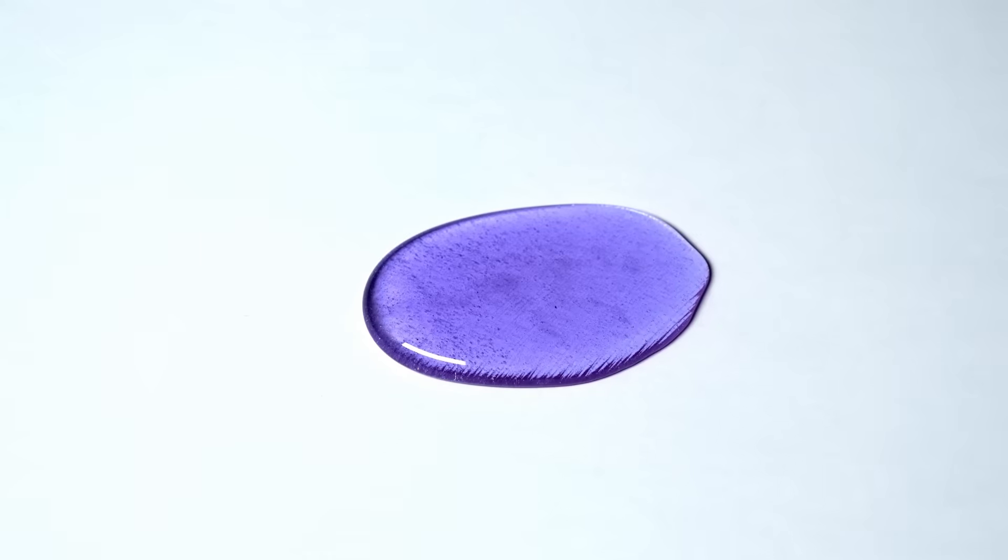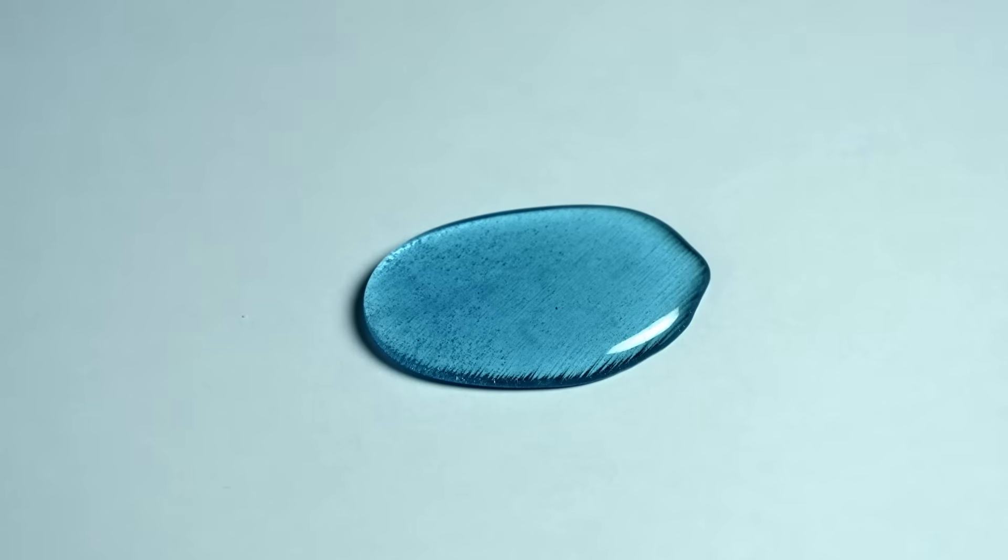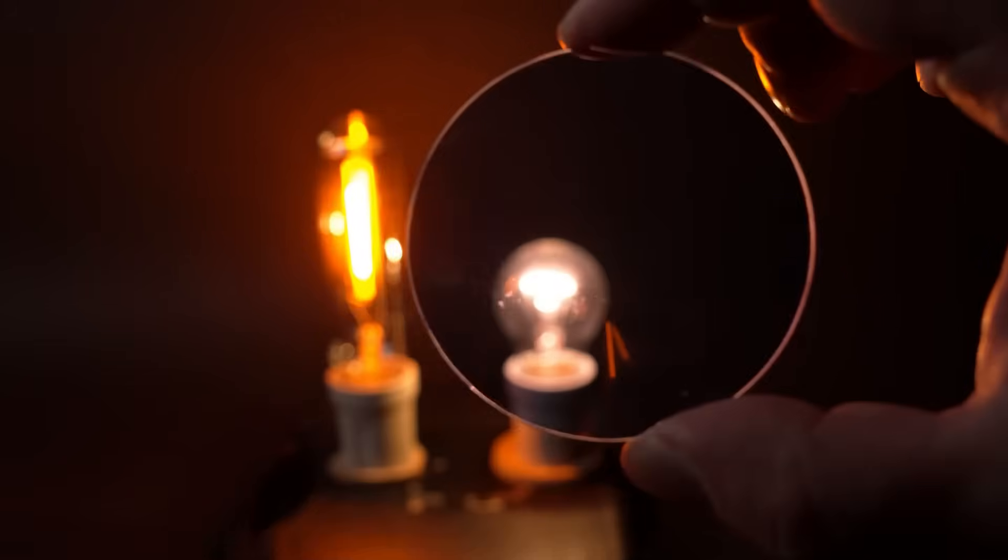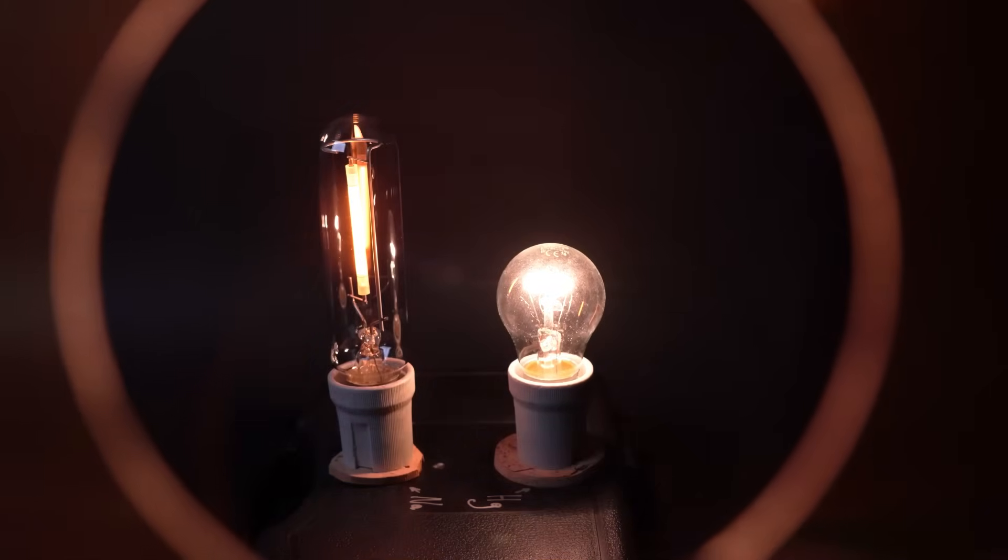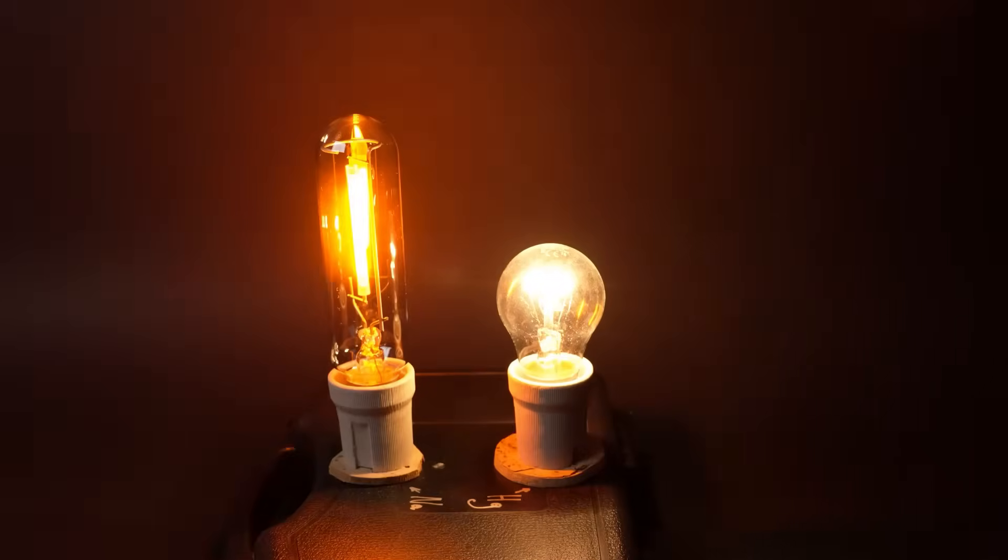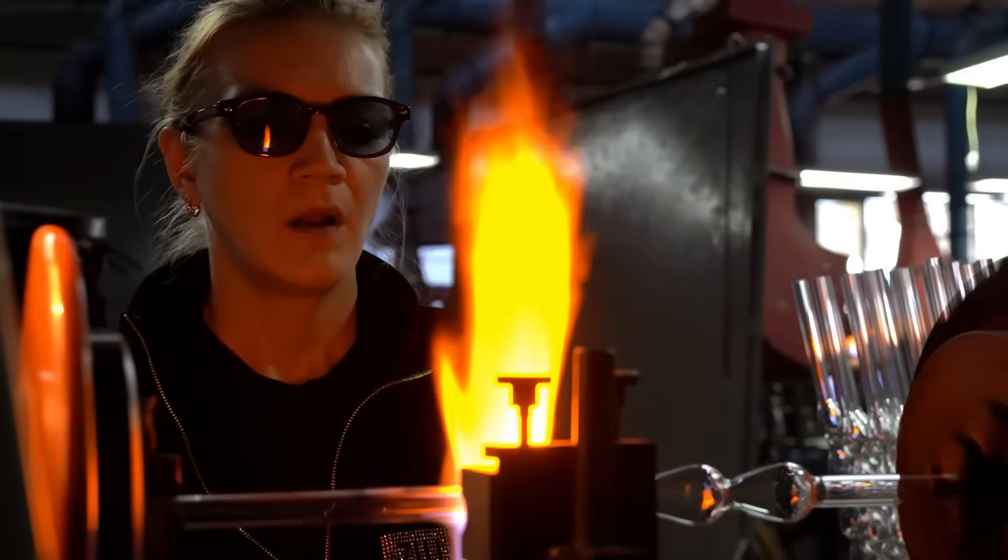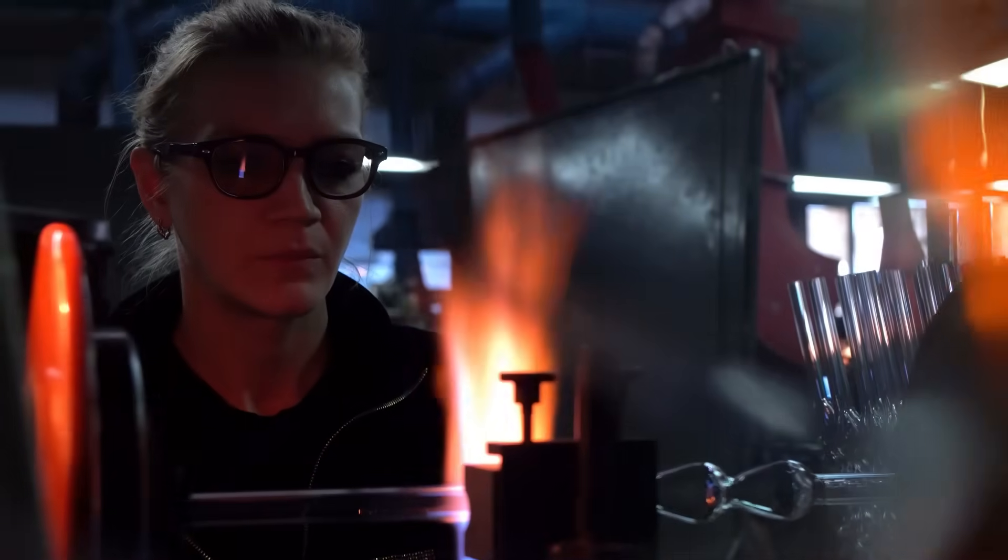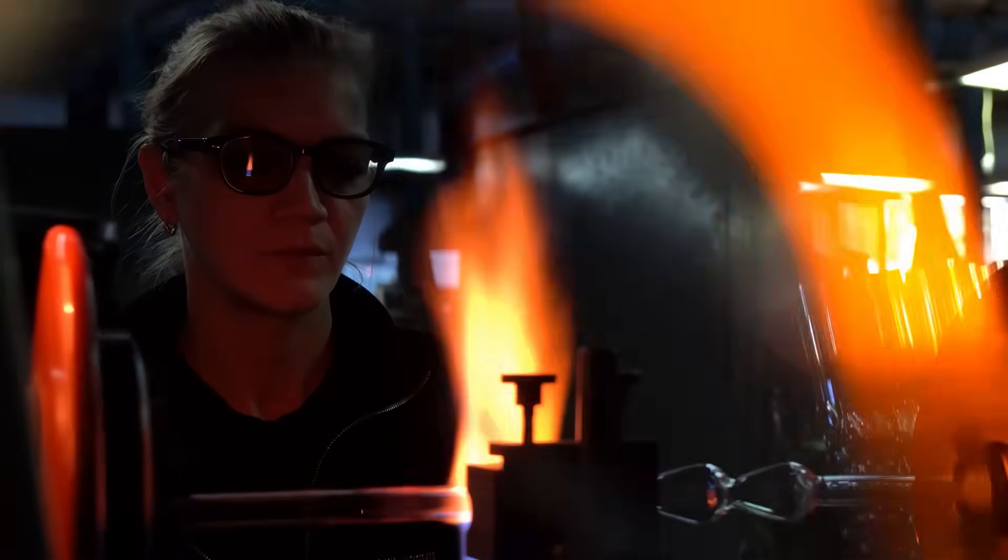After annealing, the glass did not crack at all and I ended up with a rather beautiful piece of neodymium glass, which much like the oxide of this metal can subtly change its color depending on the lighting. Under LED light, it prominently appears purple, but under a fluorescent lamp, this piece of glass distinctly turns blue, which is indeed quite unusual. In addition, this type of glass is capable of blocking the yellow spectrum of light, for example from an incandescent bulb or from a sodium street lamp. That's why neodymium glass is often used as a filter in the film or photography industry. Also, glasses with neodymium glass are often used by glass blowers, since it effectively blocks the bright yellow light from sodium ions, allowing craftsmen to work with glass without unpleasant glare. Well, I finally found a truly suitable mixture for the glass and discovered that rare earth metal oxides dissolve perfectly and completely in it. I think I can try to make an analogue of uranium glass that can glow under ultraviolet light.